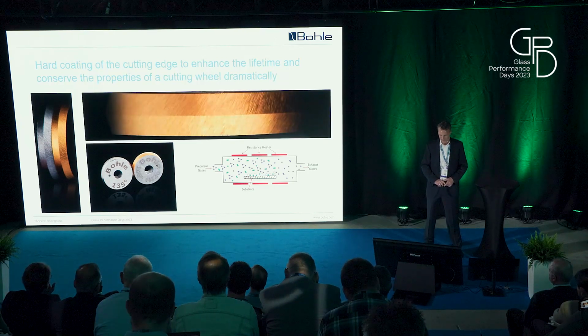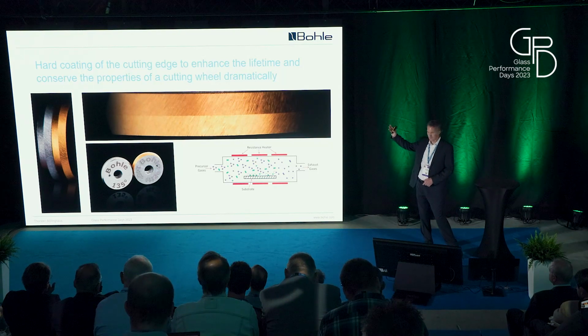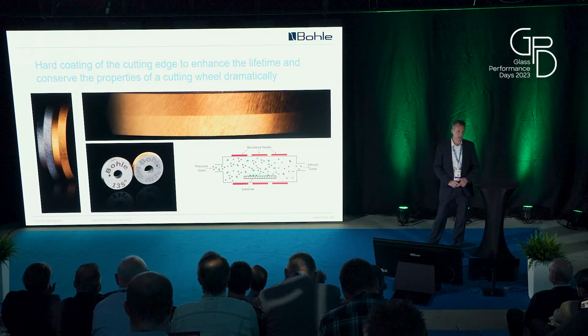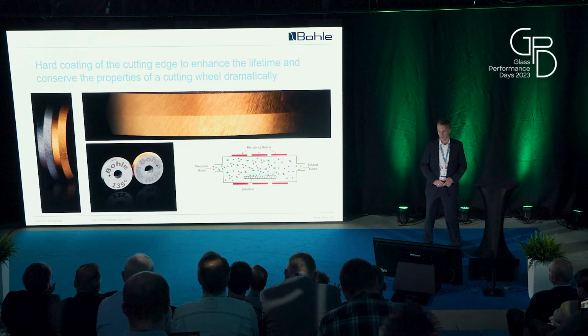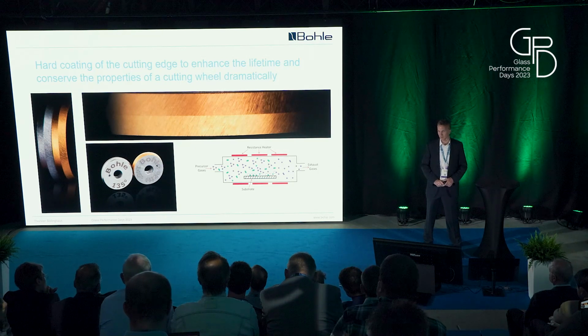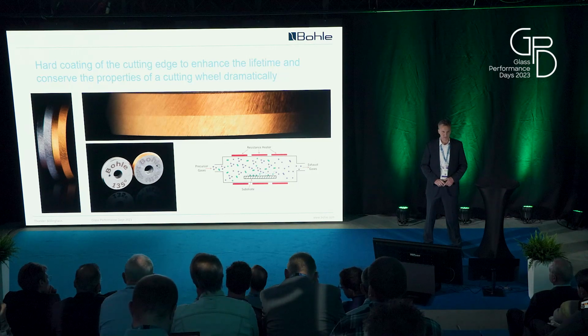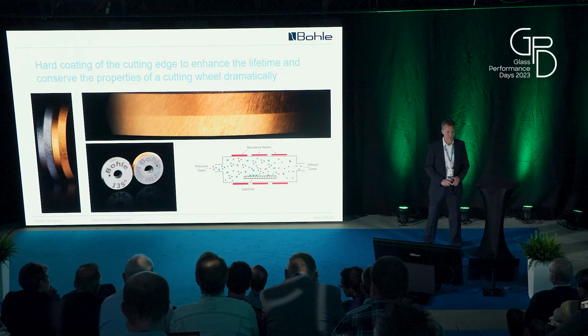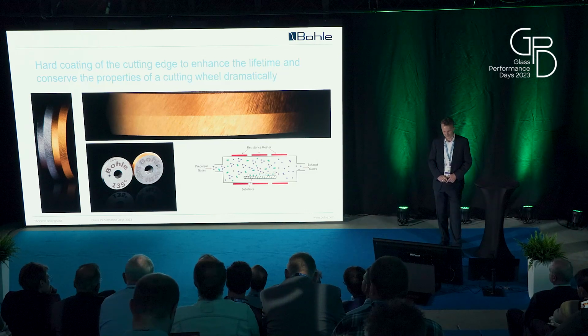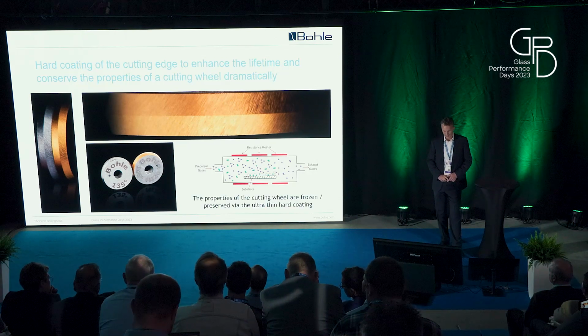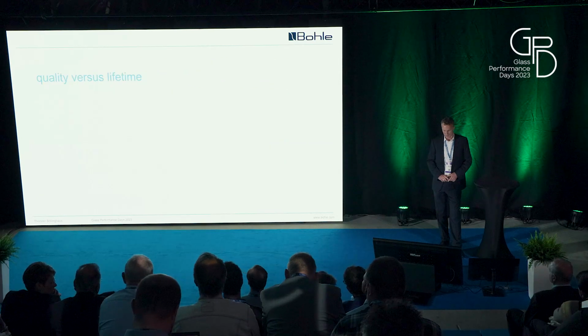And what you see in the picture here is also that you have an ultra-thin coating, and the properties of the wheels are conserved. You still see the grinding structure and everything of the wheel, and this way you can enhance the lifetime of the wheel dramatically without using the very expensive material of diamond. So this brings us to